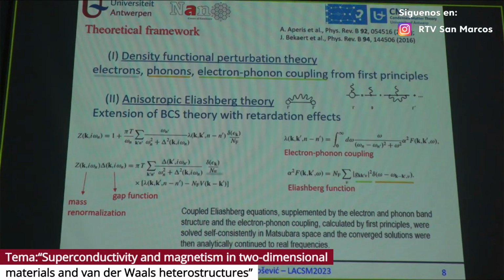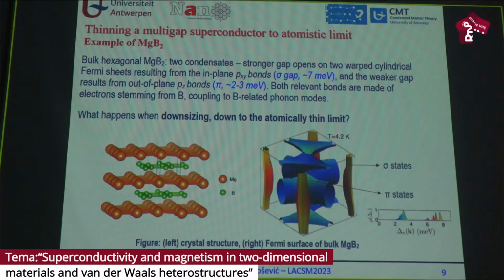And the electron-phonon coupling will, of course, yield the critical temperature, or the strength of superconductivity, if you want. But we need to do anisotropic Eliashberg. We really need to know how much superconductivity we get from each electronic band that is crossing the Fermi level. And this is a very complicated calculation.